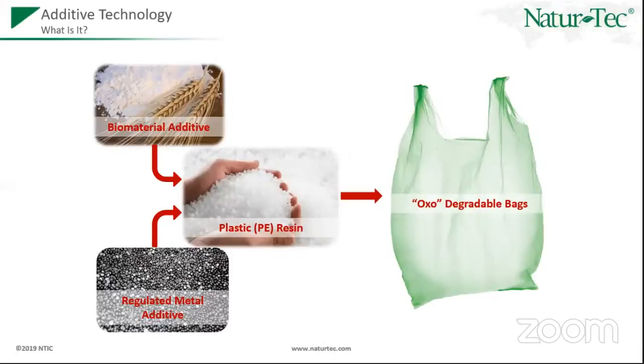Now, there are some technologies, what we call additive technologies. Sometimes there are cases where certain additives, it could be either an enzymatic additive or a regular heavy metal or a regulated metal additive, which is made as a master batch and added at 1% or 2% levels into plastics to create oxo-degradable or photodegradable or enzyme degradable products. Now, there is nothing different in these technologies. The chemistry or the science behind an additive technology is very simple. The additive essentially breaks down the polymer chain and reduces the molecular weight of the polymer.